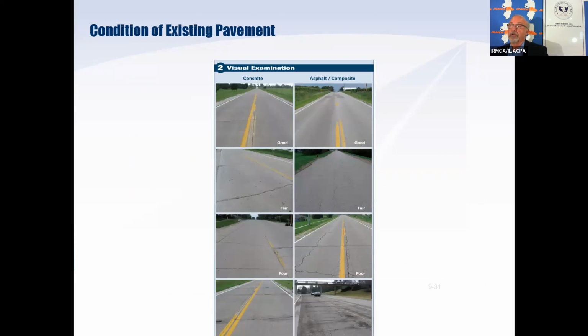So the condition of the existing pavement is obviously important. If it's in good condition, bonded overlays are a fitting solution. If it's in very poor condition, very likely you're going to be building an unbonded overlay with a separation. Keep in mind that if you're putting a concrete overlay on a concrete pavement, whatever distresses are existing in the existing concrete will likely reflect through to the surface. The same is not true for putting a concrete overlay on an existing asphalt pavement. We may have to fix areas of structural failure in the asphalt, but we don't have to do much surface preparation. The asphalt modulus is so much lower than the concrete that if you have cracks in the asphalt or you have minor alligator cracking or other types of distresses, they won't propagate through the concrete.